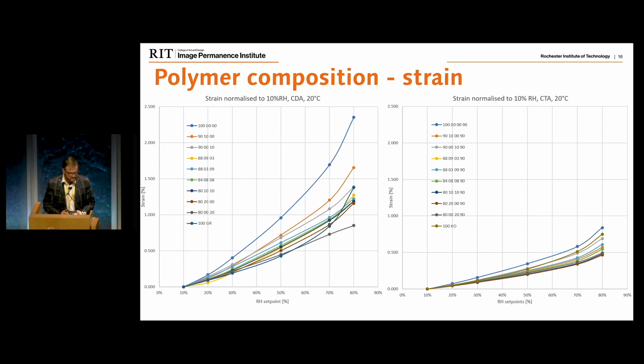response to the humidity, so what you're seeing here is the strain. So if you remember the curve, right, these points are essentially the strain at the end of each step. So this is fairly simple. Those two are the same. This is diacetate, this is triacetate. They are at the same scale. So you can see the difference of how those two respond. And you can also see how nicely they sort by the type and amount of plasticizer. The commercial materials that we have bought or acquired behave slightly differently, probably because they have different types of plasticizers in them. But our prepared samples that we know what's in them, you can clearly see how they respond.